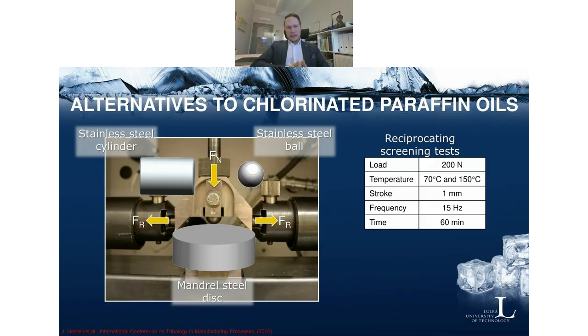So I'll start with the tube forming process, or the cold pilgering process that I mentioned a couple of slides back. So we tried to simulate this by using our reciprocating optimal SRV tribometer. We tried different configurations, and we tried a stainless steel cylinder on a mandrel steel disc. So we basically took the real materials and made them into test specimens. And we also tried just a stainless steel ball on a mandrel steel disc.